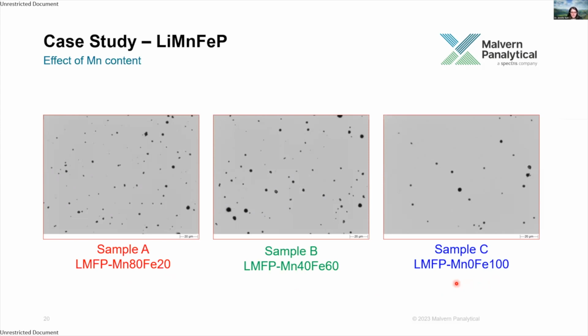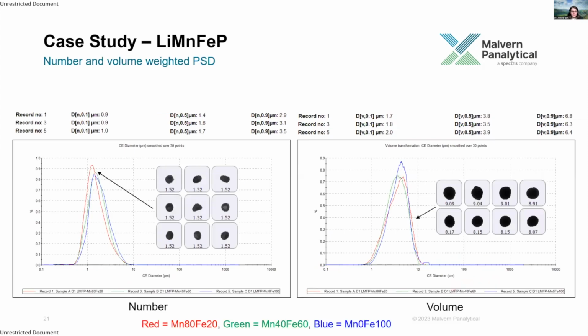So each was dispersed under the same conditions using the integrated sample dispersion unit of the Morphologi 4, and automated image analysis was performed at 50 times magnification. And for each material, tens of thousands of particles were measured, which gave us good statistical significance. So the primary output of image analysis is a number-based distribution, which we can see here on the left. Hopefully what you can see is that there is a small shift towards smaller particle sizes as we increase the manganese content of the material, but you can probably see from these percentiles, these differences are fairly minor.